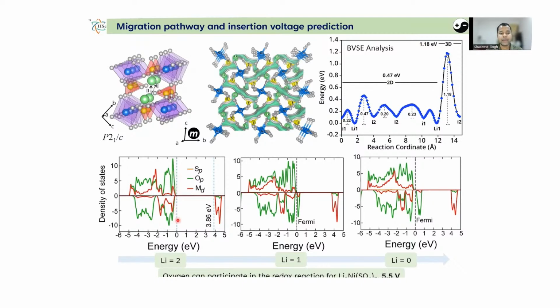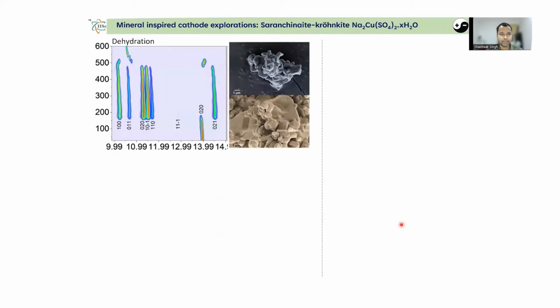So we see here the density of states at lithium 2, 1, and 0, and all along we see the high contribution of oxygen 2p orbitals near the Fermi energy levels, and that indicates the electron compensation will occur from the oxygen 2p orbitals. So in all, this material is a high voltage 5.5 volt material, which will employ an anionic redox for the electron compensation. These can be tested in ionic liquid electrolytes and other highly stable, salt-concentrated electrolytes.